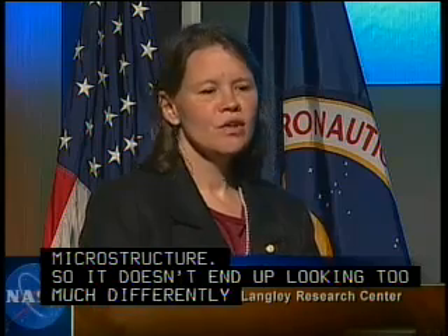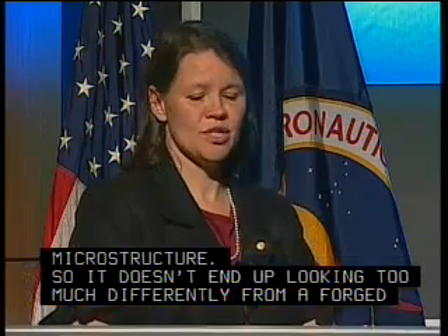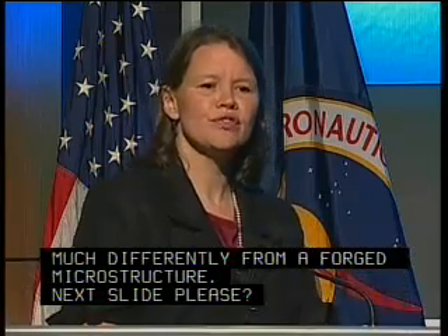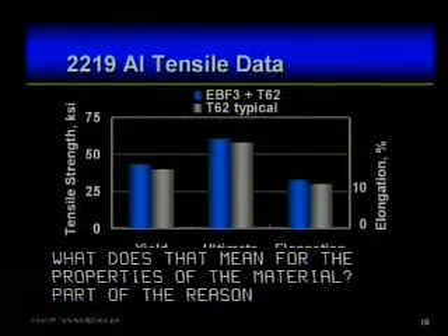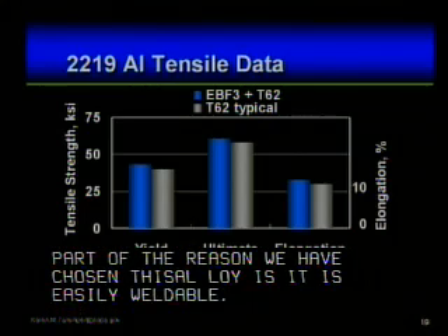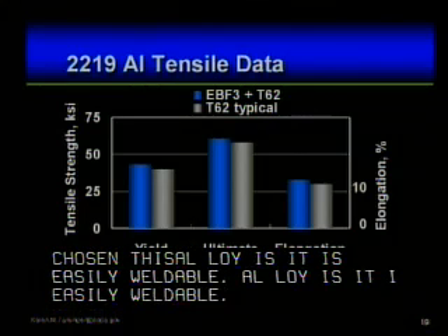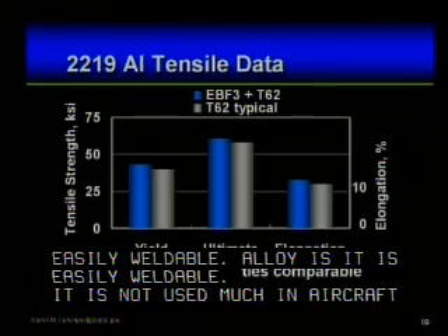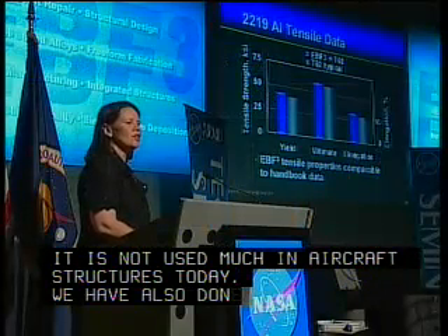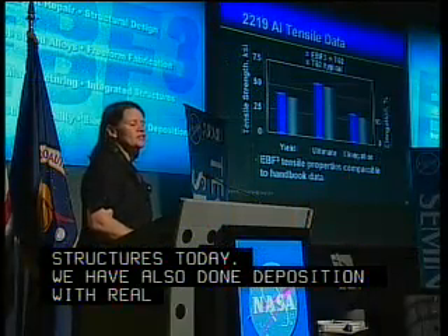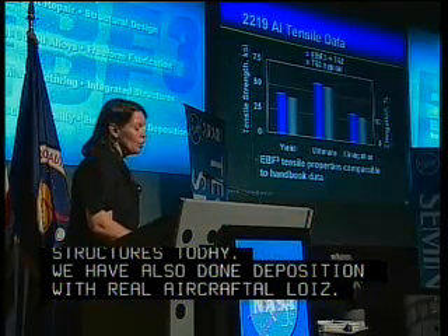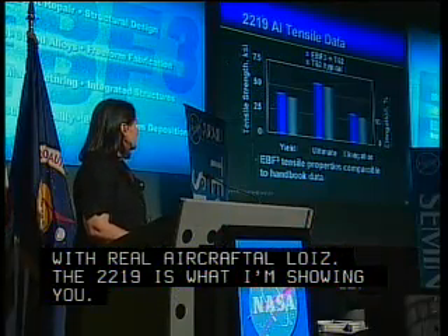Next slide, please. So what does that mean for the mechanical properties of this material? 2219, part of the reason that we've chosen this alloy is it's an aluminum 6% copper alloy. It's very easily weldable, and it's readily available. It's used in the space station. It's not used as much in aircraft structures today. There are higher strength alloys that are used today. But we have also done deposition with other real conventional aircraft alloys. So the 2219 is the alloy that I'm showing you, but we have done extensive testing on a variety of other alloys as well. What this chart shows you, on the vertical axis on the left is the tensile strength,